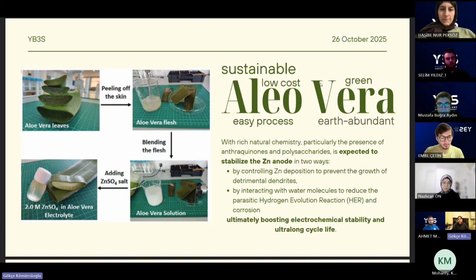Why did they use aloe vera? This plant has a rich natural chemistry, and the presence of quinone and polysaccharide in this mucilage, in this gel, is expected to stabilize the zinc anode in two ways. By controlling zinc deposition to prevent the growth of dendrites, and also the aloe vera is interacting with the water molecules, so the parasitic hydrogen evolution reaction and corrosion are being reduced.